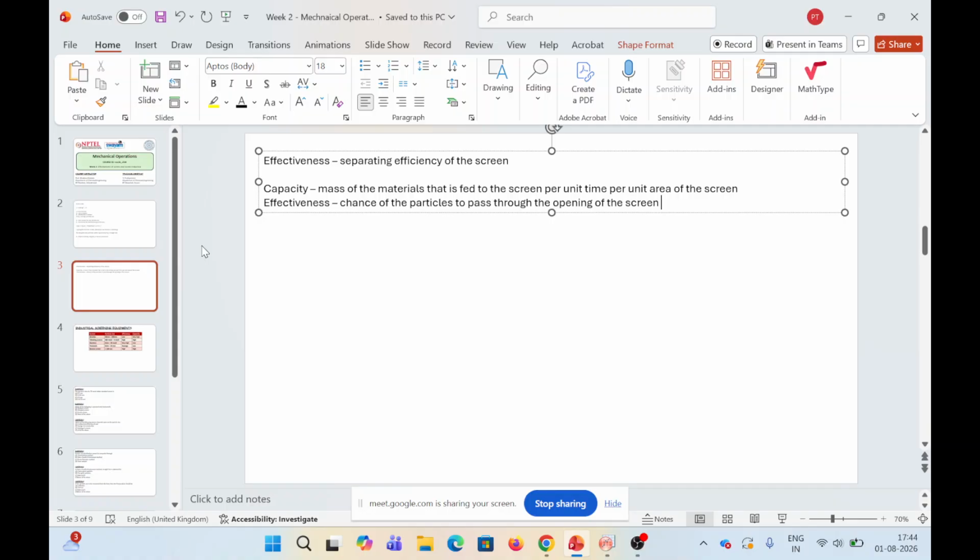Because of this orientation, irregular particles may not be able to pass through the openings, and even in those cases, the effectiveness of the screen is going to decrease. Hence, for reproducible results, you need to repeat the PSD analysis, or the screen analysis, three to four times, and provide a certain type of motion to these screens so that you give more chance for the particles to